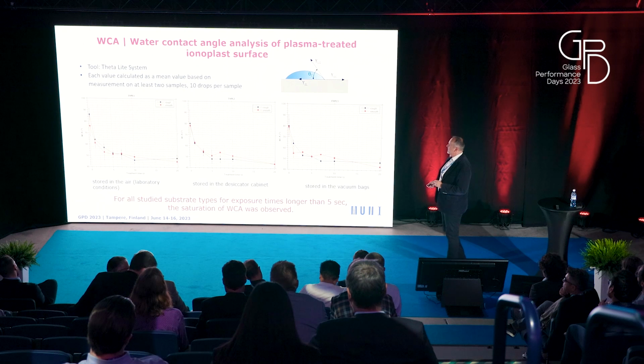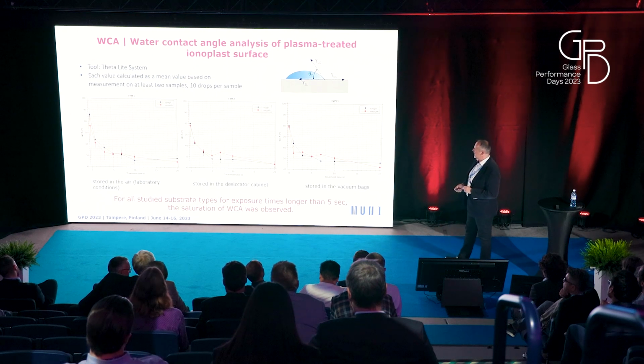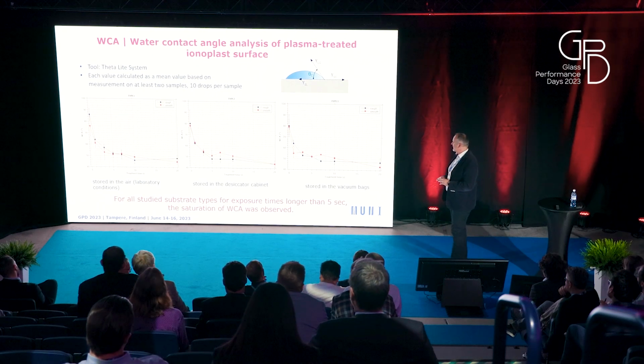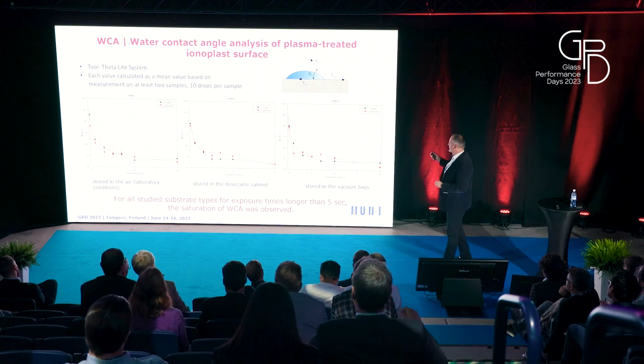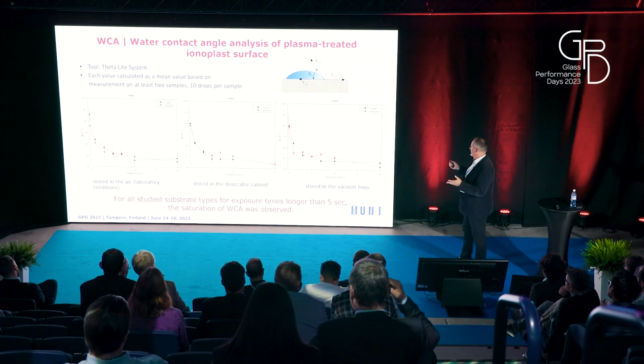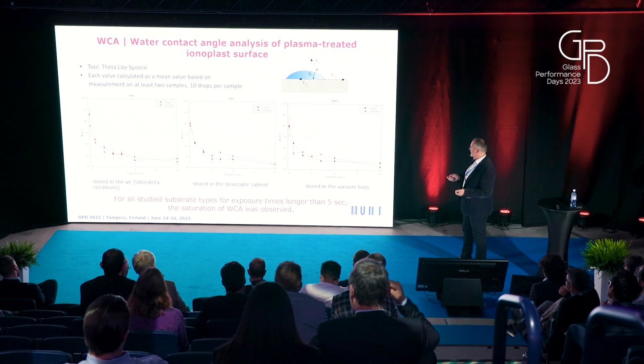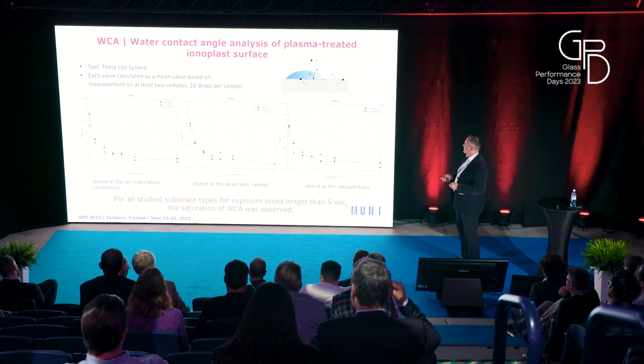And as the optimal treatment time, we consider 5 seconds. In this case, longer exposure time did not affect the results, because we observed saturation.